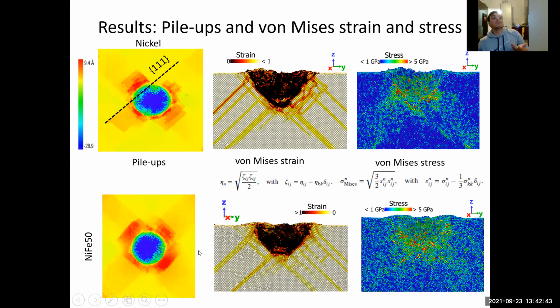And then what is happening when you are adding 50% of iron? For 50% of iron, the geometry of the pile-ups changes. And then also the strain, you have the maximum in the depth. And you can see that here you have the other dislocation, not present for this tip, and also for the stress.